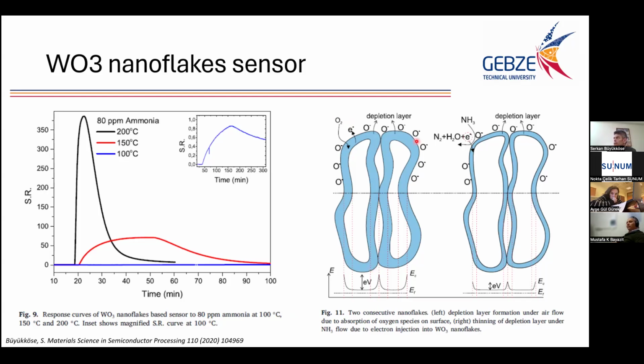So with the adsorption of this oxygen, electrons are trapped, and there is an increased space charge region here. And after exposure to reducing gases, some electrons are released back, and this space charge region decreases, which decreases the potential barrier here, and it increases the conductivity. So it appears as the sensor signal in our case.